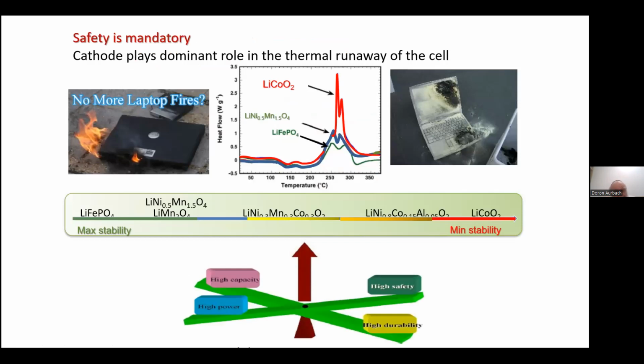In terms of thermal stability and stability in general, we have lithium iron phosphate. Lithium iron phosphate is a cathode with very mild specific capacity. It's only 160 milliamp hour per gram, and the voltage is 3.5 versus lithium. But it appears that when we compare cells comprising lithium iron phosphate to any other cells, we can demonstrate very prolonged cycle life, an order of magnitude higher. We can talk about maybe 10,000 or 15,000 cycles with graphite and lithium iron phosphate, and the thermal stability is much better by far than any other electrode material.